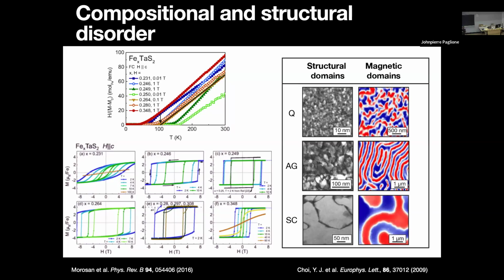And we also have known for a long time that for a particular composition, if you grow the crystals and you cool them at vastly different rates, like you quench cool versus slow cool, as is the case in many systems, you end up with very different sizes of magnetic domains. And so this sort of composition and structure disorder is well established.